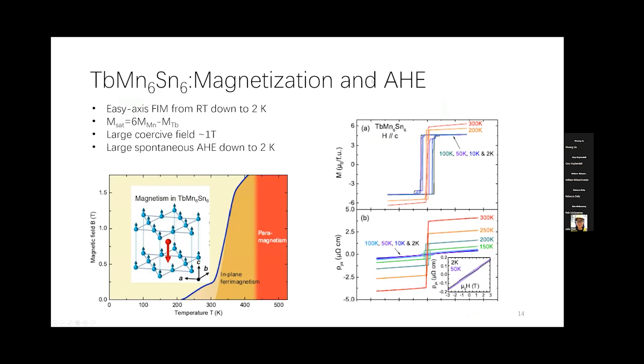This is the magnetization and anomalous Hall properties for TbMn6Sn6. It has an easy axis ferrimagnetic state, which is very stable from 300 down to 2 Kelvin. And the saturation moment equals 6 manganese minus 1 terbium. And it's a hard ferromagnet. And it also has a large spontaneous anomalous Hall effect, which follows the magnetization curve well. Also, even at 2 Kelvin, you see a very clear hysteresis loop in the Hall resistivity, indicating a detectable anomalous Hall effect down to 2 Kelvin.